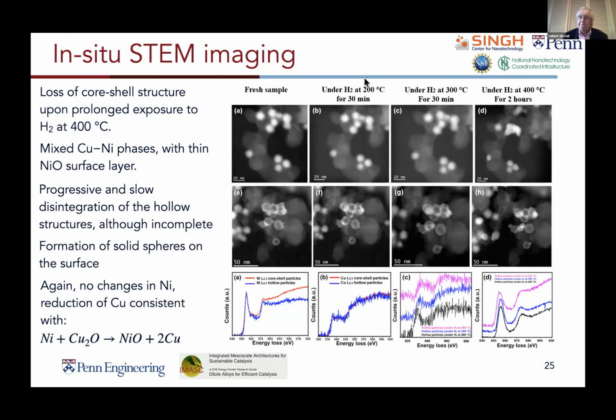Yeah, our experience has been that the electron beam really does ionize the gases, and the reactions are a lot different. In this case, what I want to indicate is that when we look at these things, we don't tend to image during the reaction. We'll run the reaction and wait to see what happens, and then you can cool the sample if you want to check, or you can do it at high temperatures. But after 30 minutes, say at 200 degrees C, you see what you see. And the short exposure for the imaging doesn't tend to do that much more. Okay, makes sense?